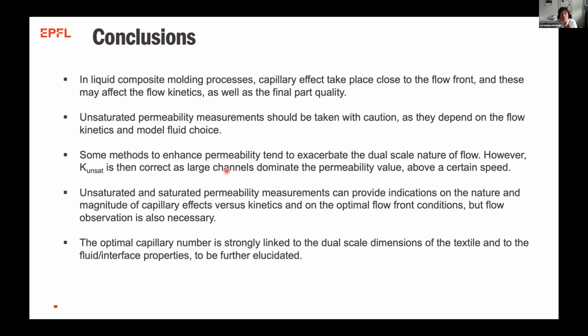But the idea was to show you that, okay, in liquid composite molding processes, whether it's normal LCM or RTM, even if you do pre-pregs or whatever, you have impregnation and capillary effects will take place close to the flow front, and they will affect the flow kinetics and they will affect the part quality. If you do unsaturated permeability measurements in your work, you should be aware that these can depend on the flow kinetics and model fluid choice. And if you want to enhance the permeability by having big channels, you also exacerbate the dual scale nature of flow. So, but the K unsaturated that you measure is correct, because since the large channels dominate above a certain speed, finally, you don't really care.